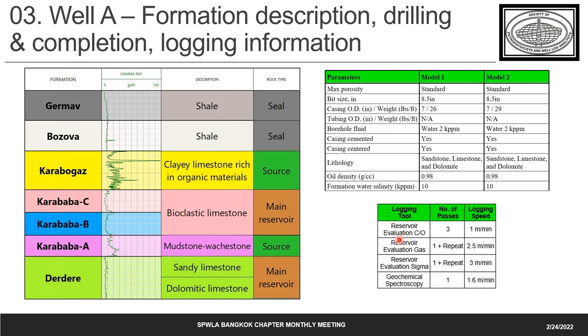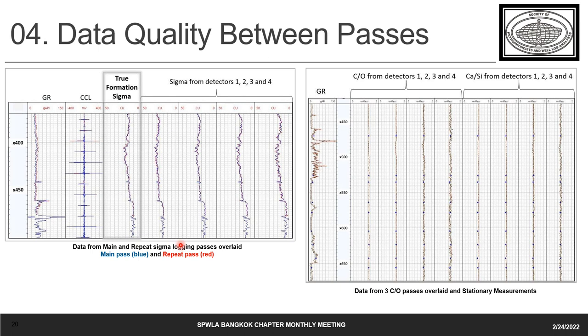Both the logging tools used in well A have a pulse neutron generator which emits between 100 and 200 million neutrons per second of high energy. Neutrons interact with the elements in the formation, resulting in the emission of gamma rays. So mineralogy is determined from the geochemical tool along with the formation sigma. And by measuring the carbon and oxygen elements, we can also determine the saturation within the geochemical tool.